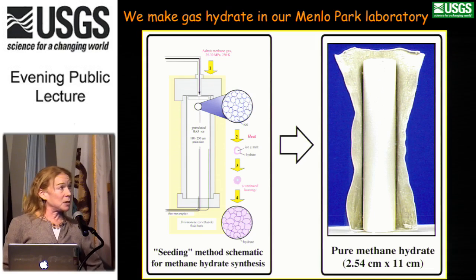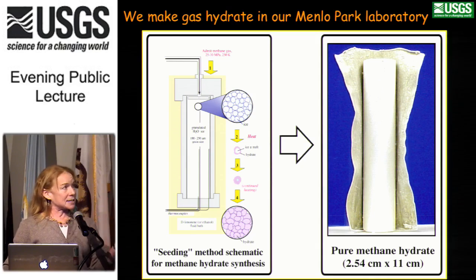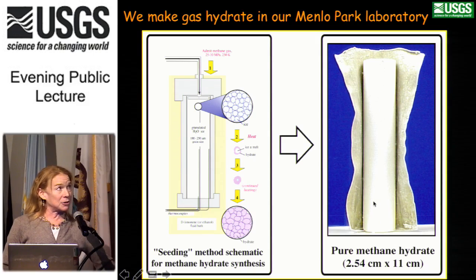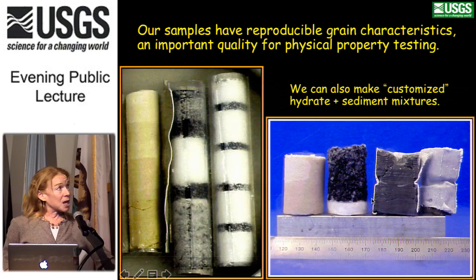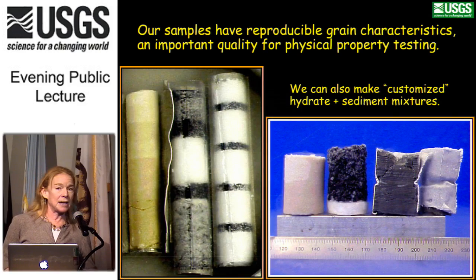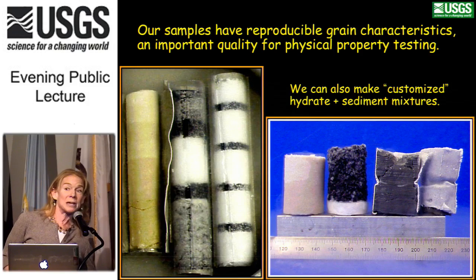We developed a technique where we take a well-prepared ice, prepared in a certain way, mix it with high-pressure gas, and we can pretty much get the reaction to go overnight to form a large stick of polycrystalline and porous methane hydrate, shown here on the right. Our method also allows us to mix in sediments in different distributions. We can do a homogeneous mix or layer it. We want to do this so that we can make tailored hydrate sediment aggregates for certain types of property tests, or to try to mimic textures from nature.